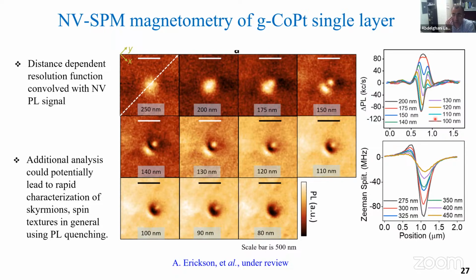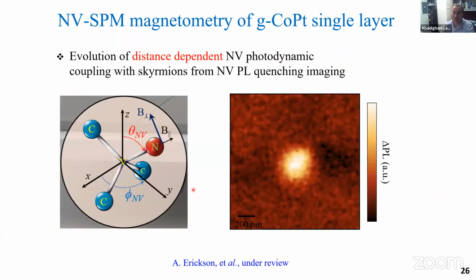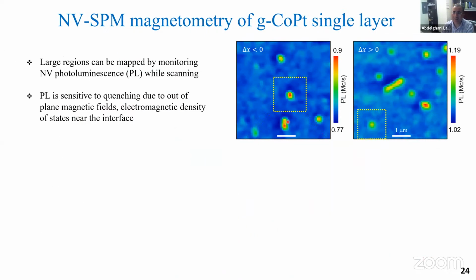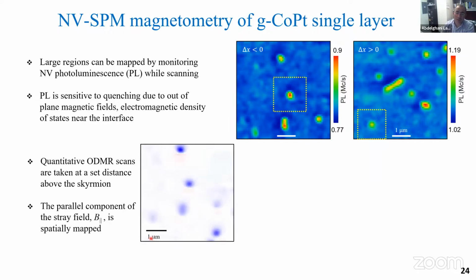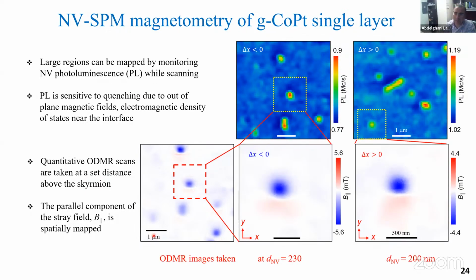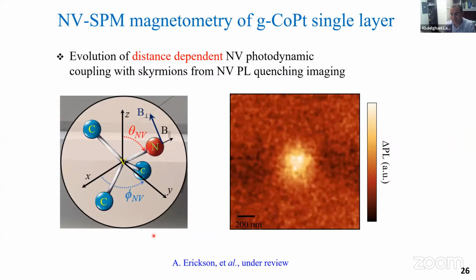While usually this is not quantitative, so you cannot in principle know the amplitude of the magnetic field generated, one can know the spatial evolution of these spin textures. More additional analysis can potentially lead to rapid characterization, because the advantage of this technique is that it is very fast in comparison. Here, you just work at a given applied frequency, so it's quick and takes a few minutes. But with the other technique, for each pixel you need to do full ODMR, and this may take a few hours. So that's why, by combining this quenching with ODMR imaging, one can map these skyrmions very nicely.